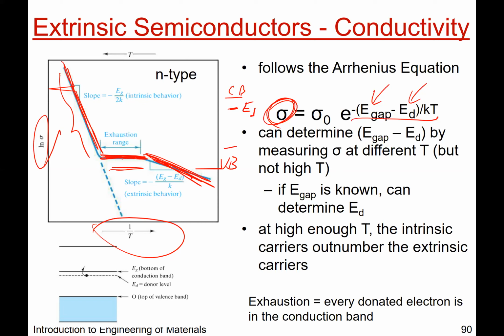So for every donated electron, for N-type in the conduction band, you can have a range where your material is exhausted. You increase the temperature, it doesn't do anything. But then as soon as you pass some threshold in terms of temperature, it'll start behaving like an intrinsic type material where you increase the temperature and you increase conductivity. Okay. So increasing temperature this way, increasing conductivity this way. So at some point, your extrinsic material will behave like intrinsic if you go to high enough temperature.